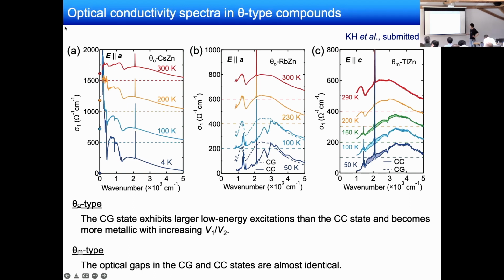And actually, these observations are very consistent with the resistivity data. But if you look at the optical conductivity spectra of this monoclinic thallium zinc compound, there is little difference in the optical conductivity between charge crystal and charge glass states, and the optical gaps are almost identical for these two states. This is also consistent with the resistivity data.